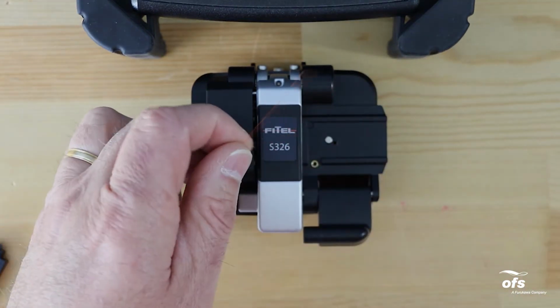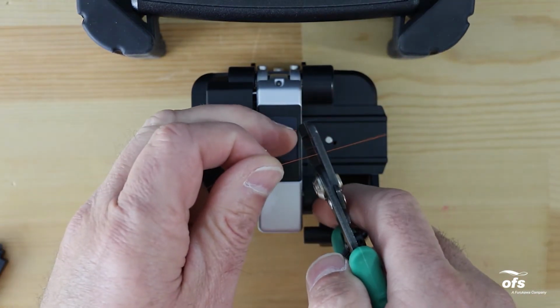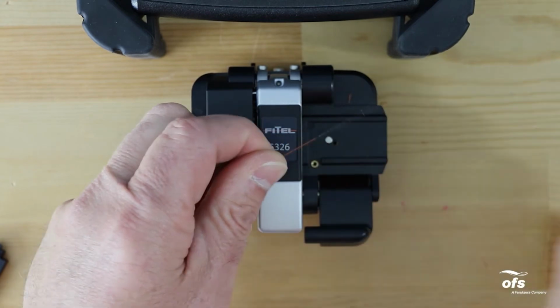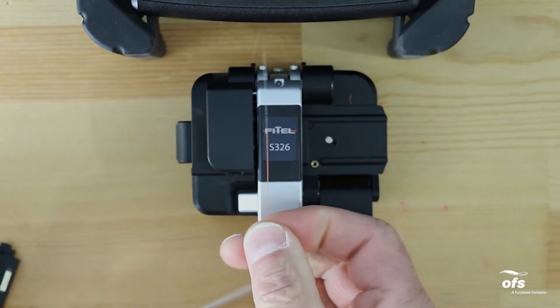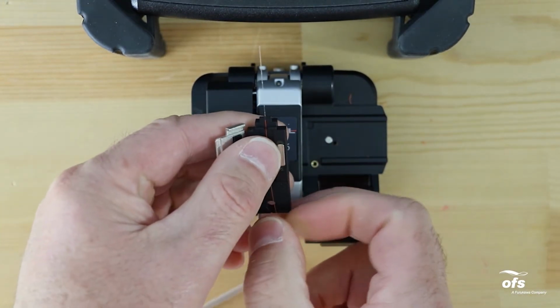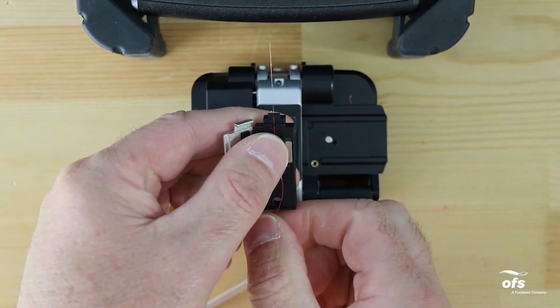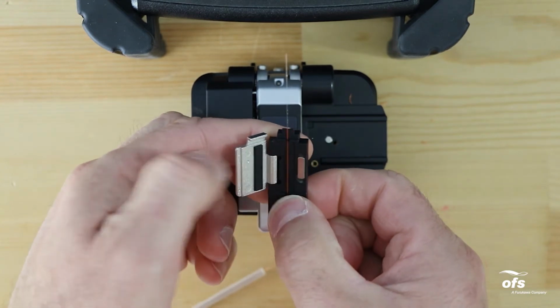If you are using 250 micron fiber coating, strip approximately 30 millimeters of 250 micron coating from the end of the fiber, leaving bare glass. Load fiber into removable holder with the coating edge even with the end of the holder, fiber curl facing down.